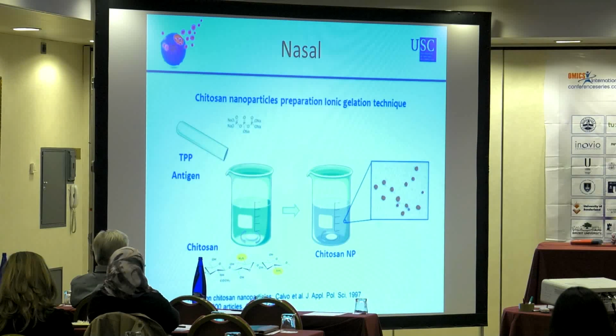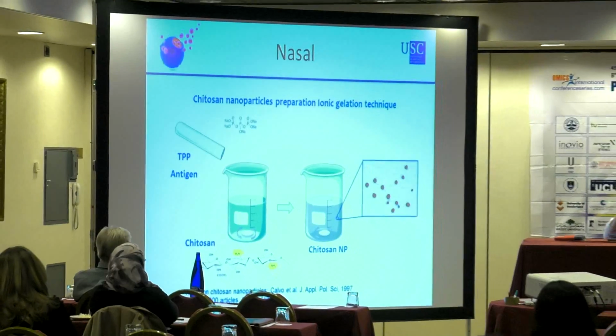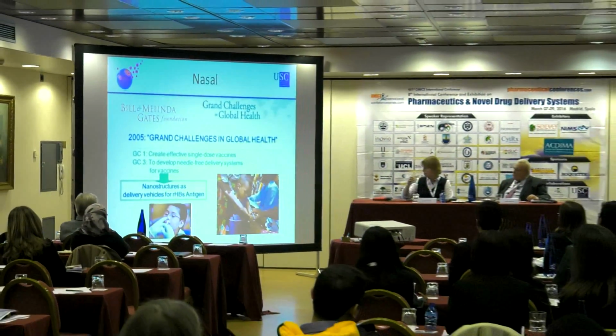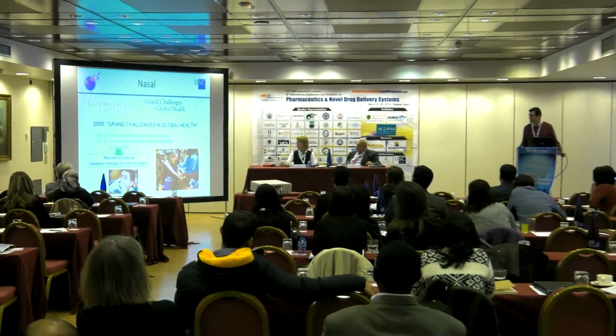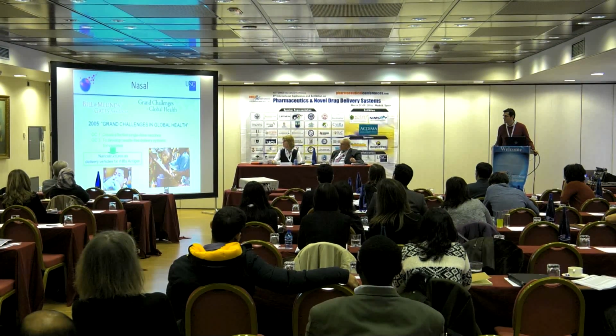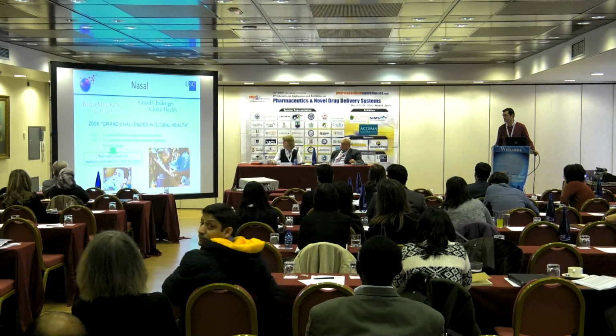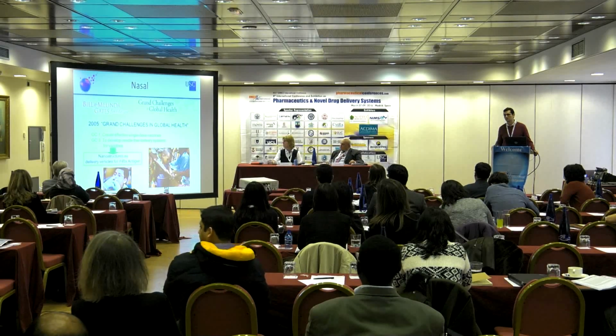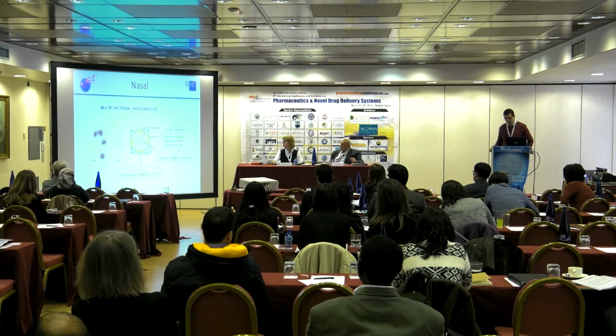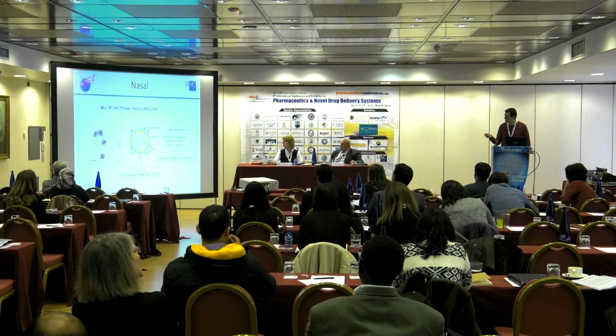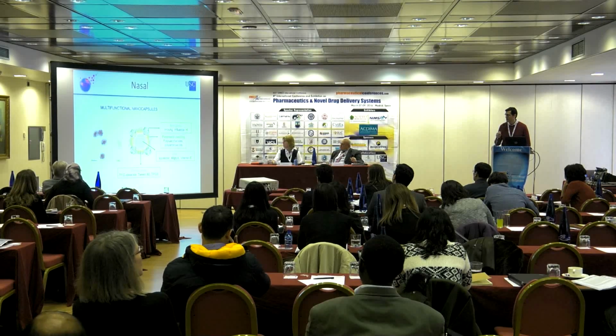In the group of Maria Jose, they were the first to report chitosan TPP nanoparticles by ionic gelation technique. These nanoparticles have been employed in different fields of nanotechnology. Then a big step happened when 10 years ago we were funded by the Bill and Melinda Gates Foundation to create a single-dose vaccine and needle-free delivery systems that are quite important in the developing countries. So we moved to different nanostructures, especially this one, the nanocapsules.